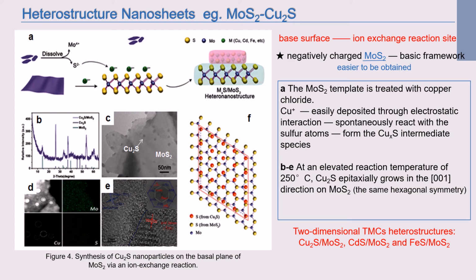As shown in Figure A, it is treated with copper chloride. The introduced copper metal ions are easily deposited through electrostatic interaction. These copper ions spontaneously react with the sulfur atoms in the highly fragmented molybdenum disulfide during the ultrasonic assisted exfoliation process to form the copper sulfide intermediate species, as shown in Figure A.